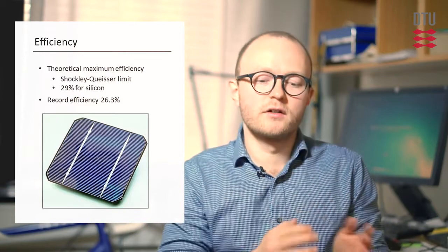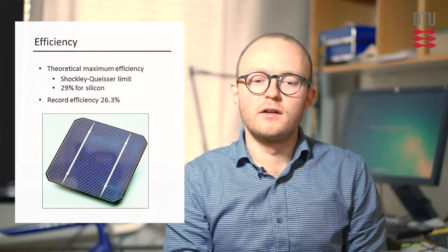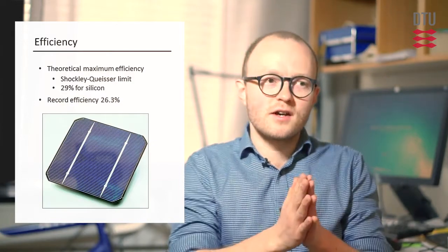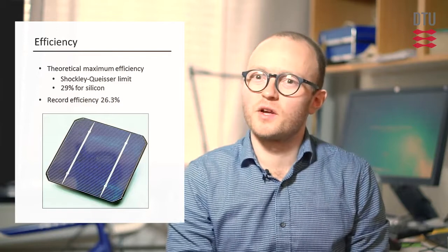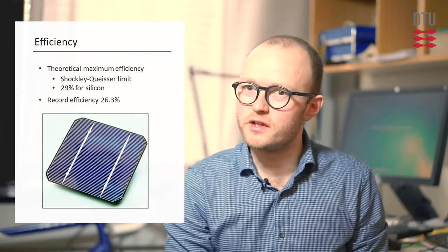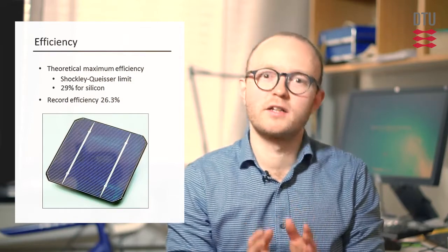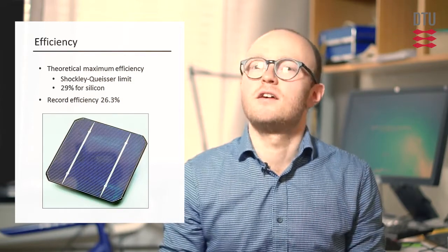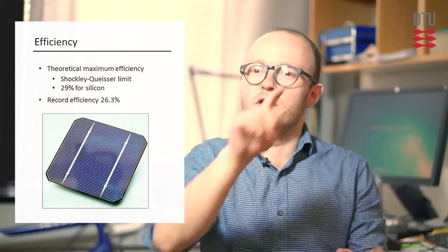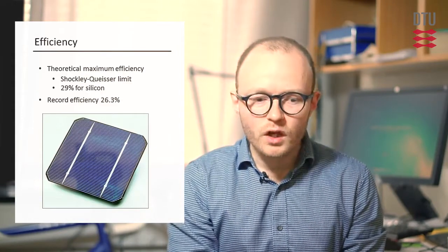And when silicon becomes thinner than, say, 100 micrometer, roughly, it starts acting like a foil and becoming quite fragile. I'm not saying that it's impossible, but it starts to become practically challenging, besides the theoretical considerations of having an optimal thickness.